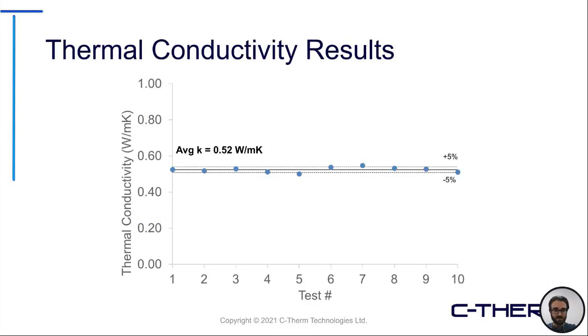So this is just a quick example. We can show that measuring this cement across 10 measurements, we get a very nice tight measurement spread. Average thermal conductivity coming out to about 0.52 watts per meter Kelvin. But really this is an example here of the material type that you're looking to test really being most appropriate for the TPS sensor.